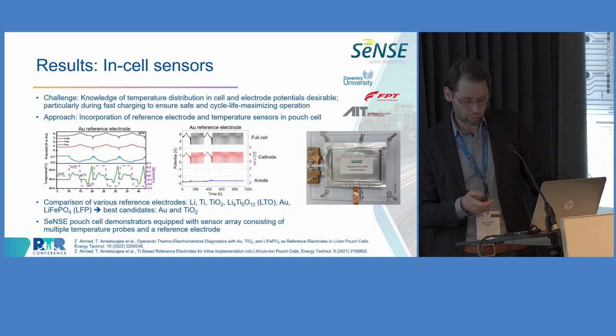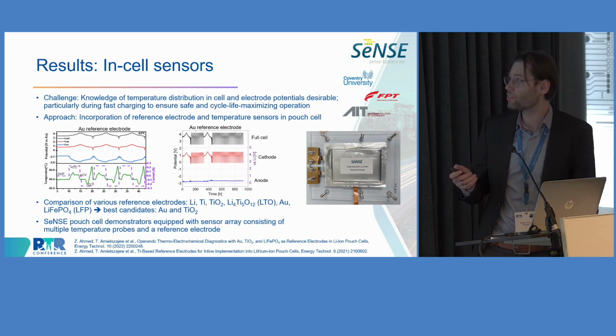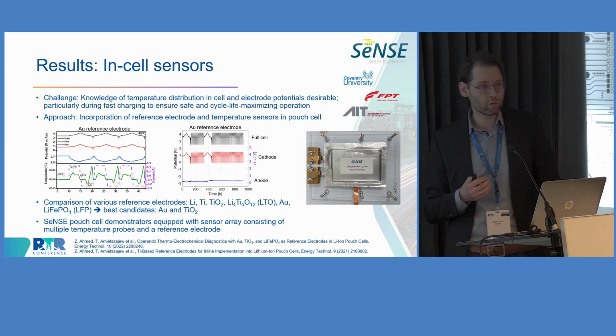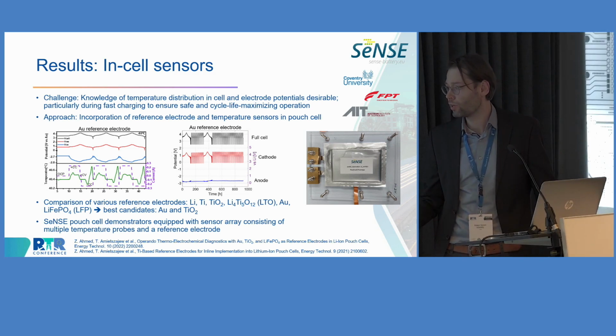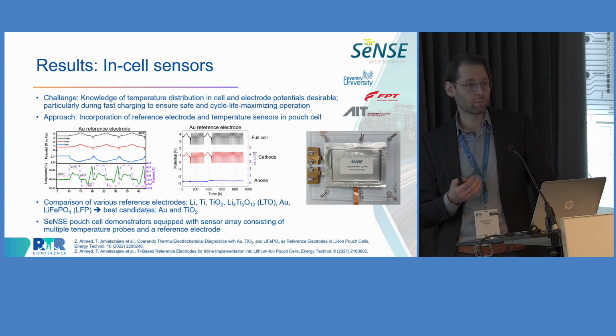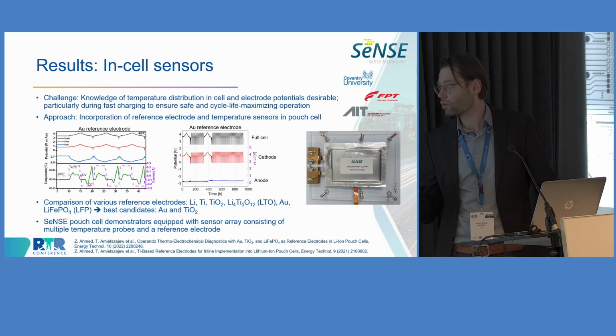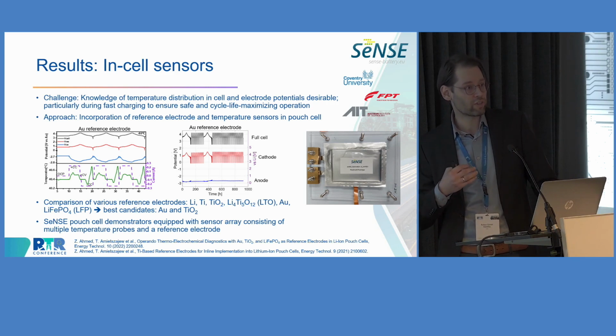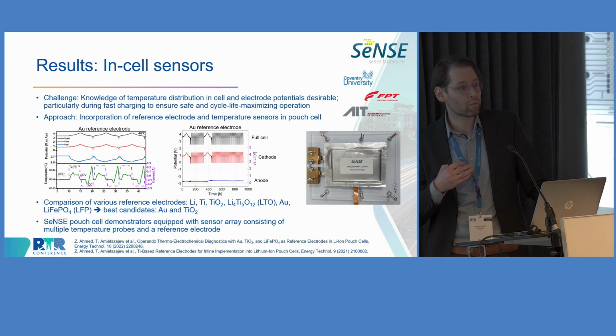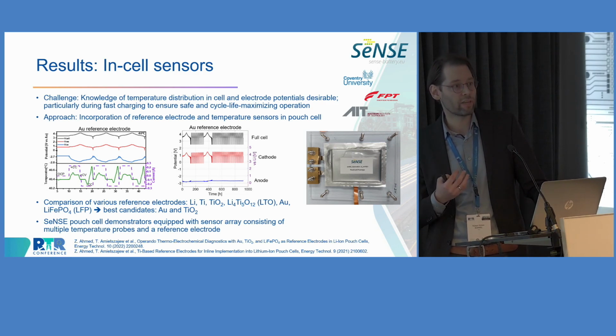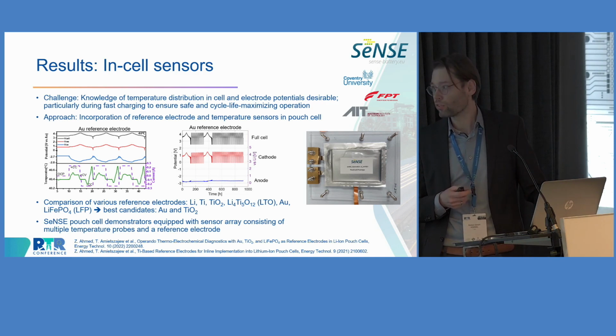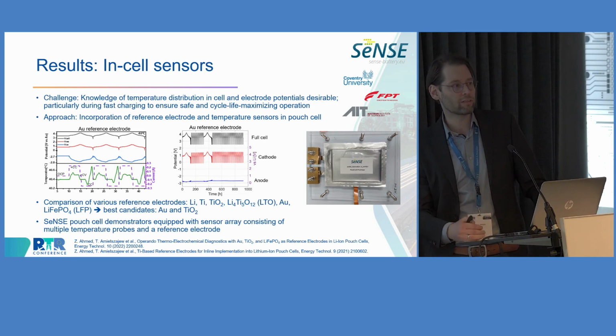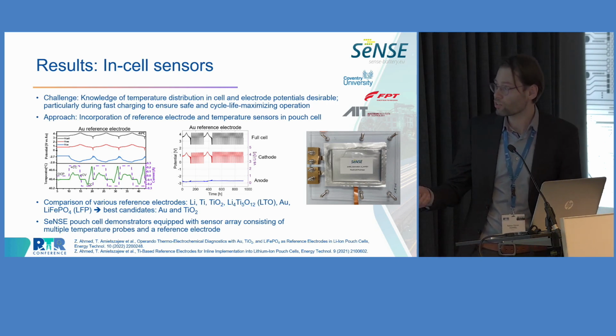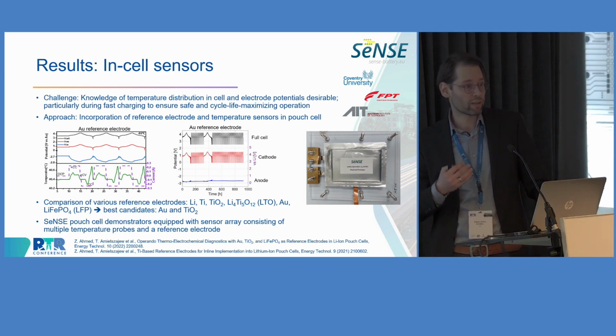The last example I would like to highlight today, I already mentioned that we're also working on in-cell sensors, and here our partner Coventry University from the UK has a lead, and they published 2 nice papers in this project where they investigated multiple reference electrodes. So we are not only interested in the temperature distribution in the cell, but also in the individual electrode potentials, which is particularly important to learn more about the state of health of the silicon-based anode, and also for fast charging, because we want to avoid states of the cell where it comes to lithium plating, right? Lithium plating meaning that the potential of the anode would drop below the lithium plating potential, and that's kind of the state you want to avoid.